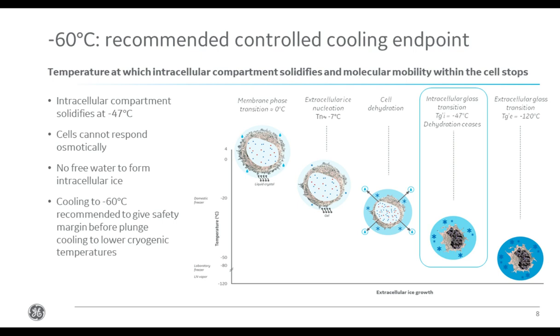After extensive dehydration, these internal components are pushed together through lack of space, and the cell can dehydrate no further. This is known as the intracellular glass transition, and cells cannot dehydrate beyond this point. When we measured this transition physically, we found it occurred at about minus 47 degrees. This makes sense. Controlled cooling is used to allow cells to dehydrate on cooling.